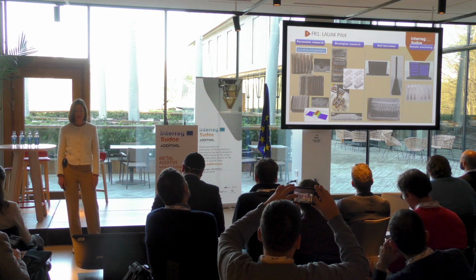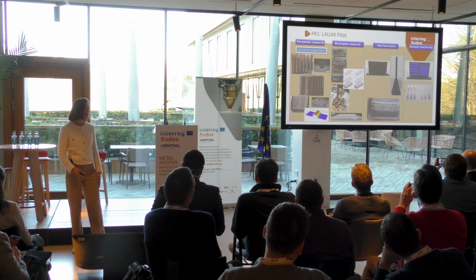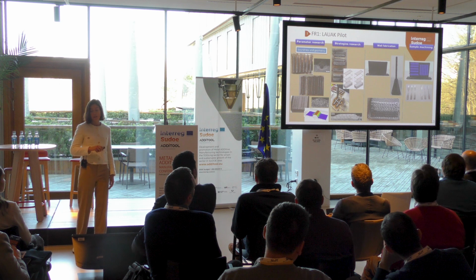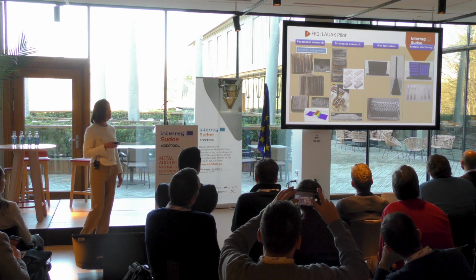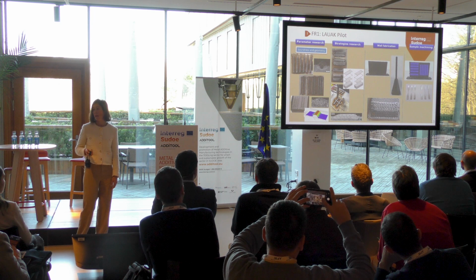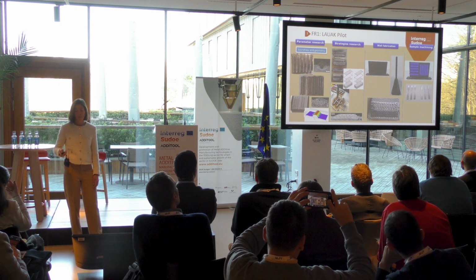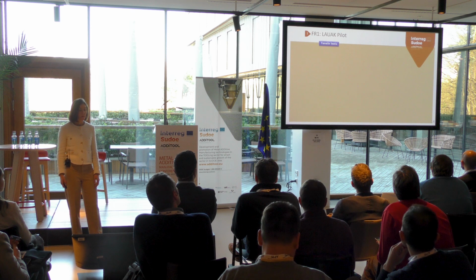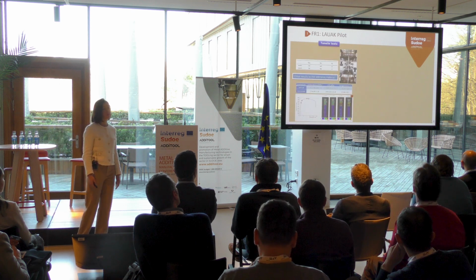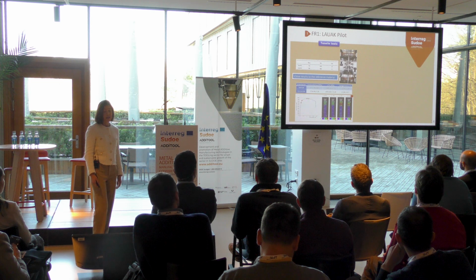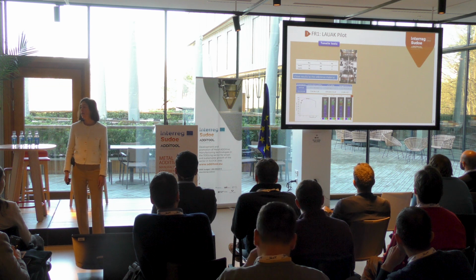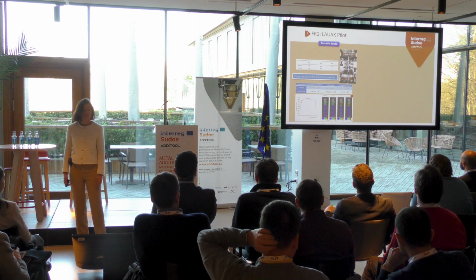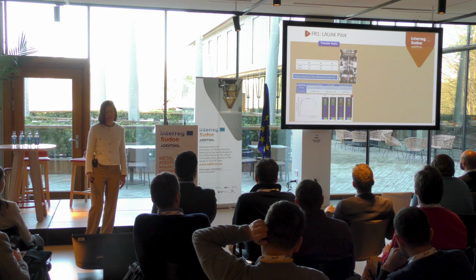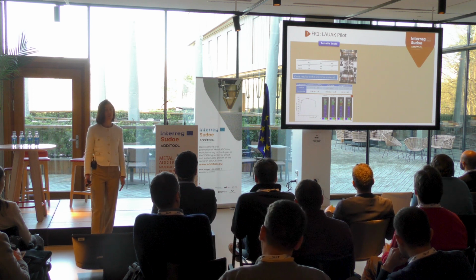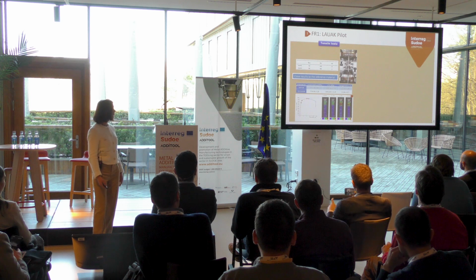From these walls, tensile tests were extracted in different orientations, horizontal and vertical, to check if any anisotropy was present. We obtained the results of tensile tests on the different parts made with the different technologies. The results were very close to the reference, and there's no anisotropy.